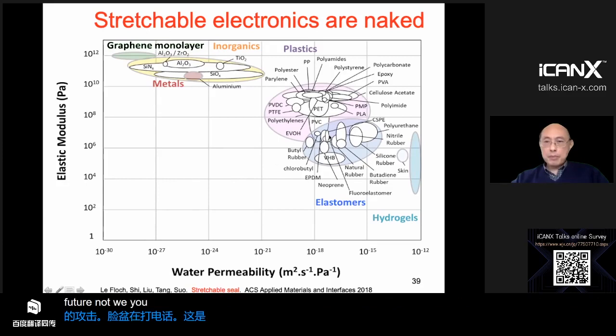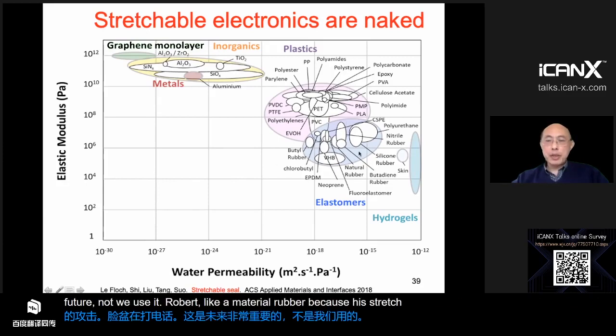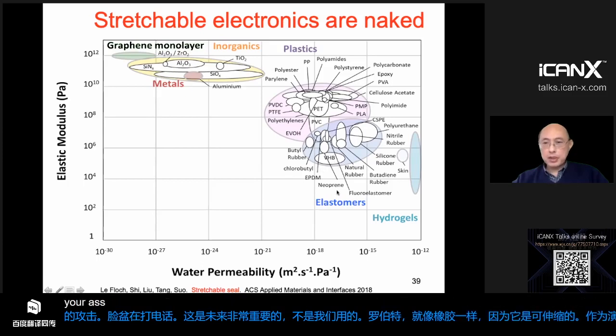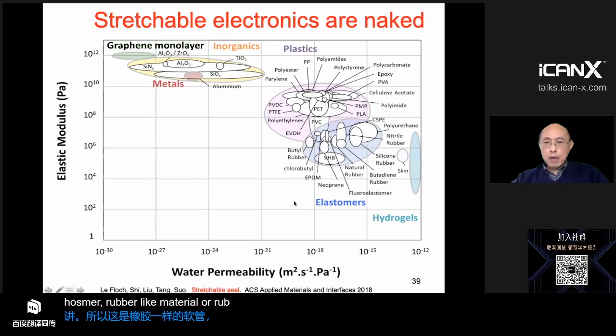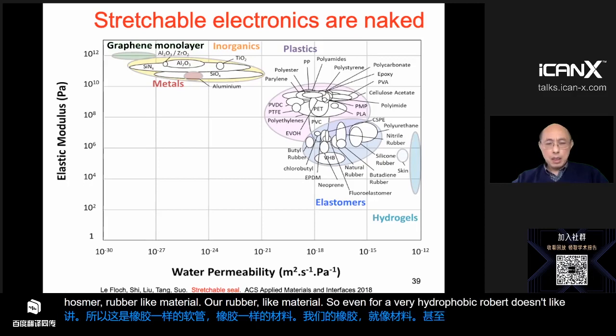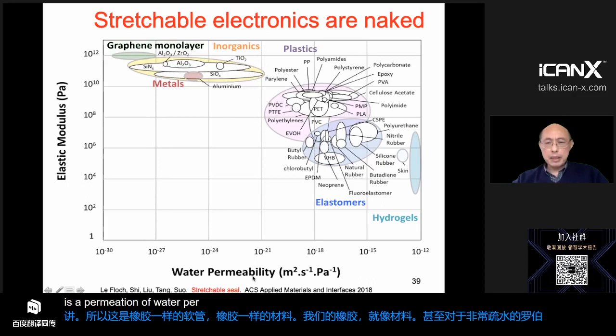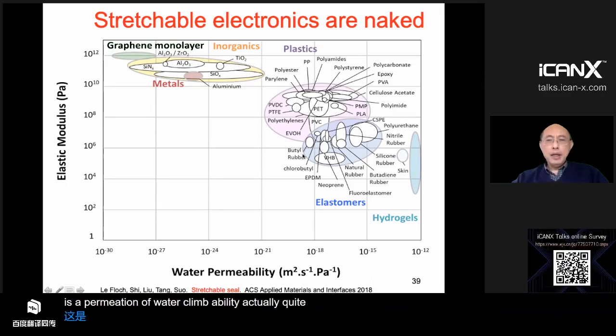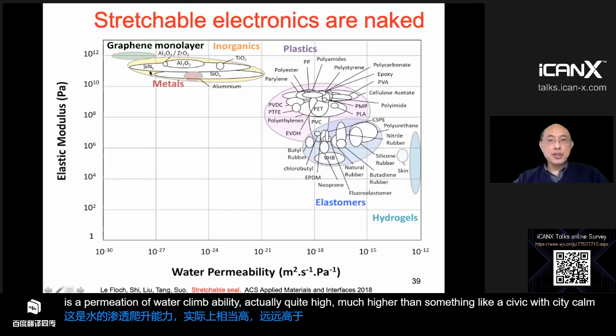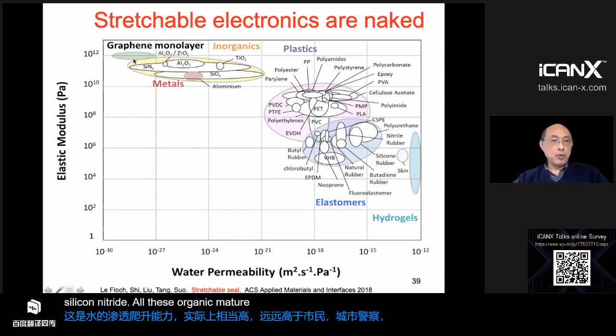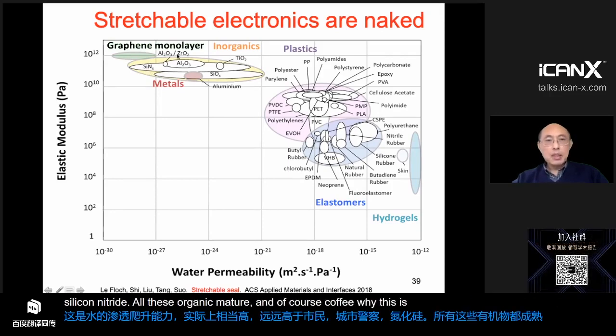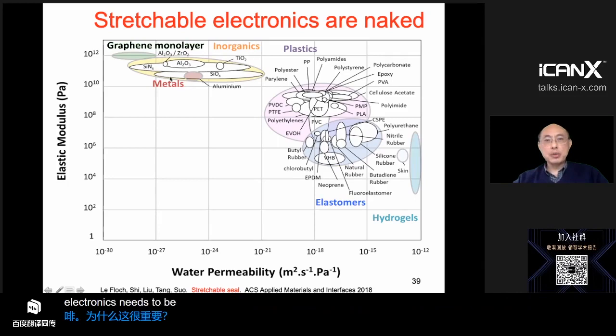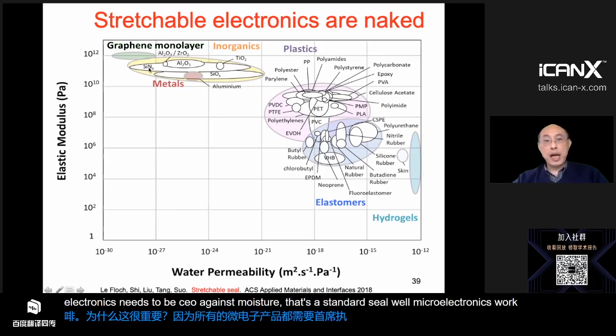Now, we use rubber-like material. Rubber is used because it's stretchable as an insulator. So this is a rubber-like elastomer. Even for very hydrophobic rubber, which doesn't like water, this is the permeation of water. The permeability is actually quite high, much higher than inorganic materials like silica and silicon nitride, and of course graphene. Why is this important? Because all microelectronics need to be sealed against moisture. That's a standard seal. Microelectronics works because you have this inorganic seal.